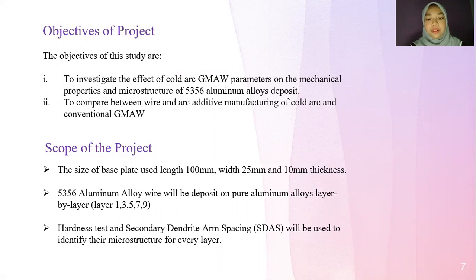Two materials have been used: a wire of 5356 aluminum alloy and a base plate of pure aluminum alloy. The size of the base plate used in this project is 100 mm for length, 25 mm for width, and 10 mm for thickness. The wire 5356 aluminum alloy will be deposited on pure aluminum alloy layer by layer, starting from the first layer. Then 4 samples of layers will be recorded, which are layer 3, layer 5, layer 7, and layer 9. To identify the mechanical and microstructure properties, hardness test and secondary dendrite arm spacing will be used.